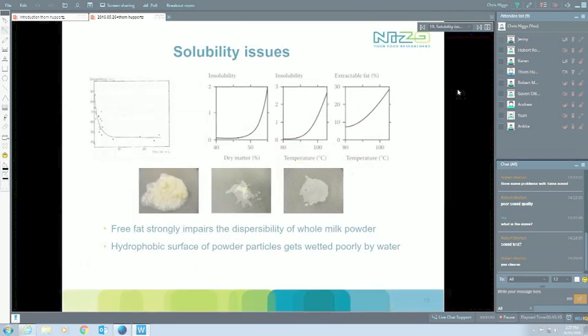Of course, it's not just oxidation that it will do. The other thing that we typically see is the more free fat, the worse the dispersibility will get, and you see that in an example here, you start seeing that decreasing very quickly. Once you reach 5% free fat, something like that, your dispersibility quite simply becomes a nightmare, and you need to make sure that you do something about it, otherwise it's going to be a long, hard road really. So that comes back to controlling emulsion stability, making sure that it's properly homogenized, that we get stable emulsion droplets there, taking into account, of course, the pressure drop that we get after atomization, if we go on with 200 bars and we drop that into the chamber, that can have effects again on emulsion stability, so we need to make sure that it's stable. We don't get any free fat issues there, we don't get it shooting off the charts and get a big issue there.